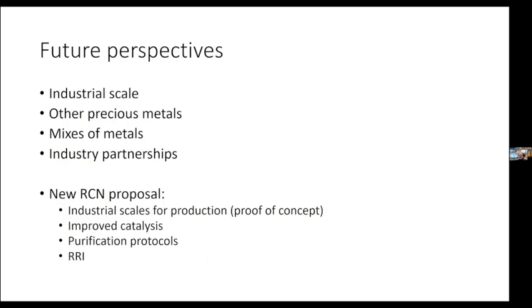As our project is now finishing, we have been thinking very hard how to take this to the next level. There are some pitfalls and problems here, but also great perspectives. We're currently preparing an RCN proposal in that regard. We would like to take this to industrial scale. We want to show that we can produce these particles not just in a test tube format or in half a liter format, but this can be taken to hundreds of liters. This is not super trivial because scaling this to larger volumes gives you changes in oxygen levels and other things that would impact redox reactions in the cell. Of course, we want to improve our catalytic properties further and improve the strains further in that regard, and we need to work on these purification protocols.